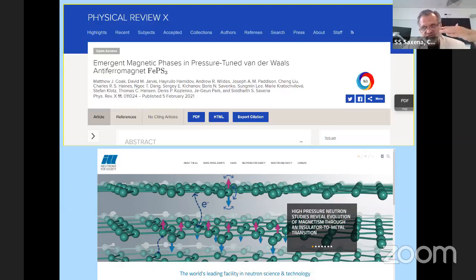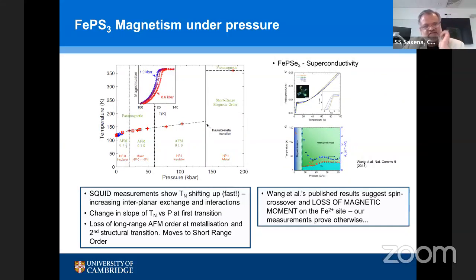But they had never gone to the lower temperatures or looked at materials which had no long-range order. In fact, the transition from a full long-range order to a fluctuating order state was quite a difficult experiment, but we were able to do it, and that produced this phase diagram.